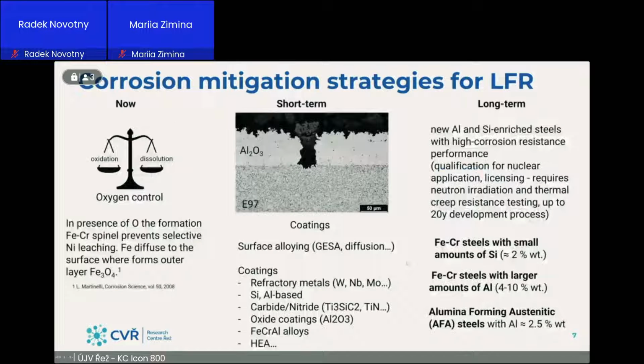So there are several mitigation strategies for this corrosion. One of them, and it's available now, is this oxidation, or growing up this oxide layer, that has some advantages. That is simple, but the problem is that it's a kind of balance between oxidation and dissolution, and it works to a certain temperature, let's say 400, 500 maximum. Then